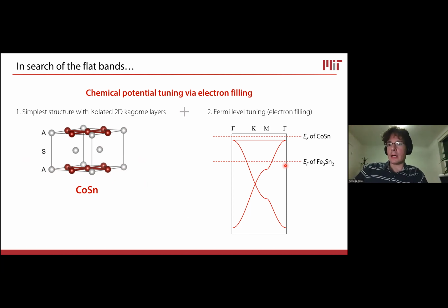And so if we look at the chemical potential in Fe3Sn2, it lies over here. So it's below the flat band. So we cannot see it with photoemission, which only looks at the bands below the Fermi energy. So what we did was we artificially raised the chemical potential with respect to these bands by substituting iron with an element which has an extra electron. So essentially, if you like, we're playing with electron filling, and we're raising the chemical potential that way.